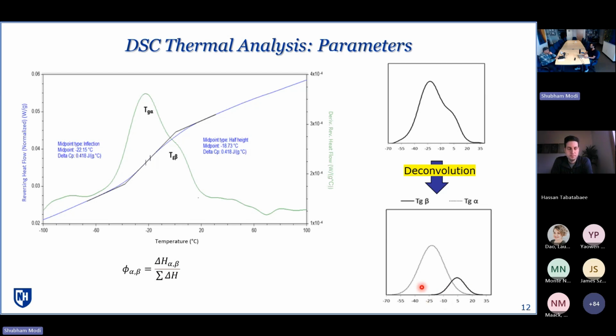So on the parameter side, we can see that the glass transition temperature corresponding to this primary peak is called Tg alpha, and corresponding to the secondary peak is called Tg beta. And the area under the primary curve is called the phi alpha parameter here, and the corresponding one for the secondary curve is called the phi beta parameter, and that is normalized with the total area covered under the curve.